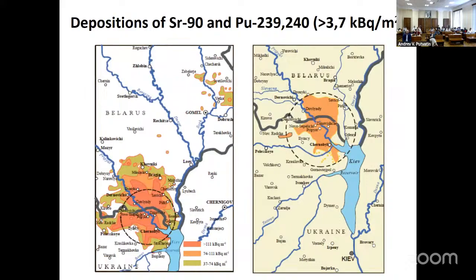So that was cesium-137. Cesium-137 is a semi-volatile radionuclide, so it evaporated during the accident at the temperature of the accident. But refractory elements such as strontium and plutonium were not evaporated and they were released together with nuclear fuel particles or nuclear fuel debris. They were incorporated in this debris. This debris was heavy. The density of nuclear fuel is quite high. And also they have quite significant size. Therefore, these particles were deposited mostly near the nuclear power plant.